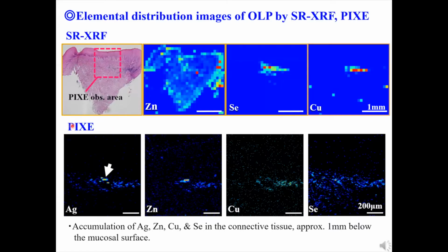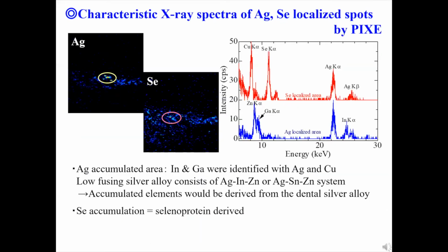Micro-PIXE could visualize the accumulation of silver in the deeper region of the mucosa. In the spot analysis at the silver accumulated region, we could find new peaks assigned to indium and gallium. Those four elements are the alloy components of the low-fusing dental silver alloy. Then, it was suggested that they most likely originated from dental alloys.